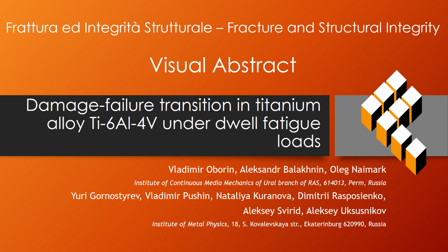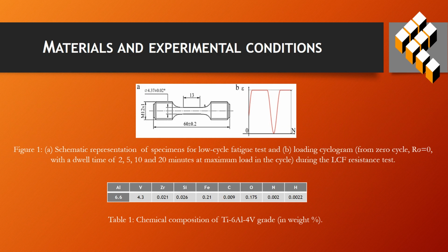The topic of our paper is damage failure transition in titanium alloy Ti-6Al-4V under dwell fatigue loads. The role of structural features of titanium-based alloys, which are responsible for the staging of damage failure transition in low cycle fatigue and dwell fatigue regimes, is considered.